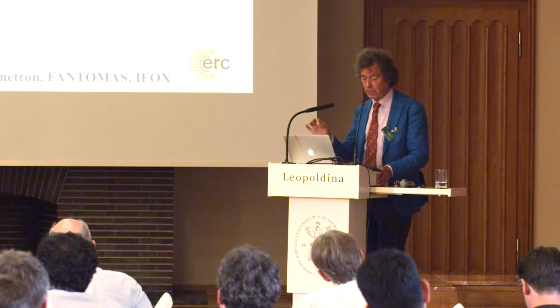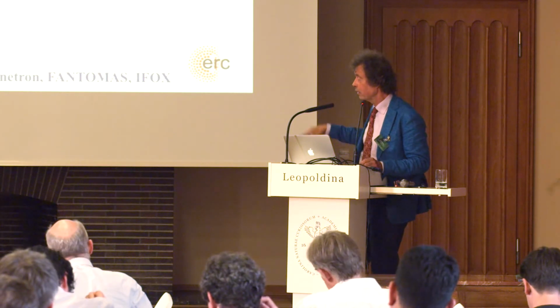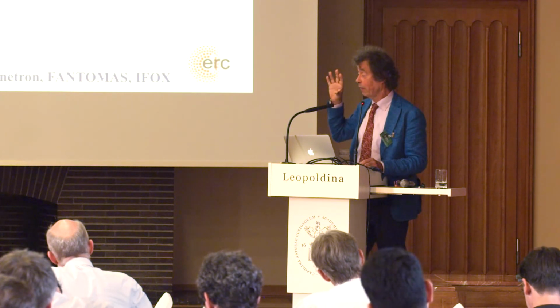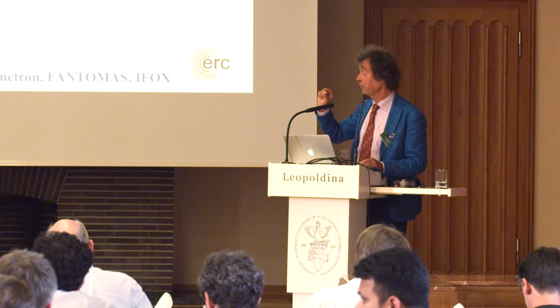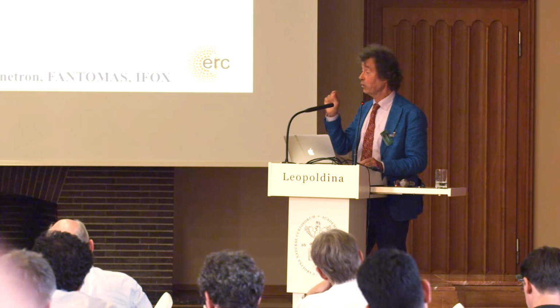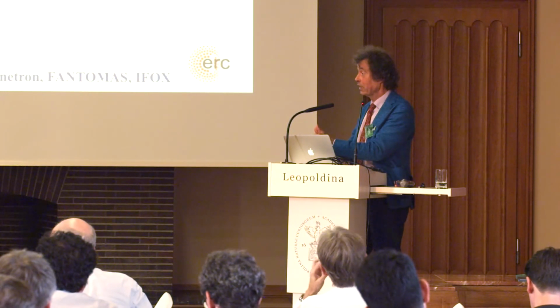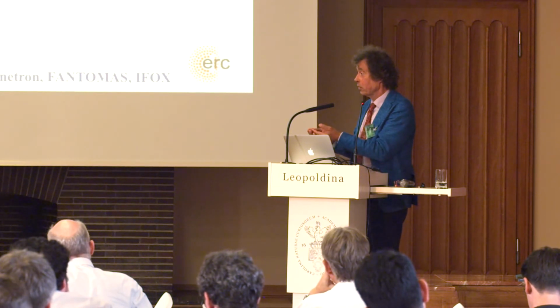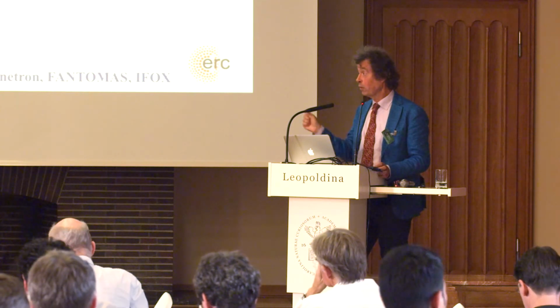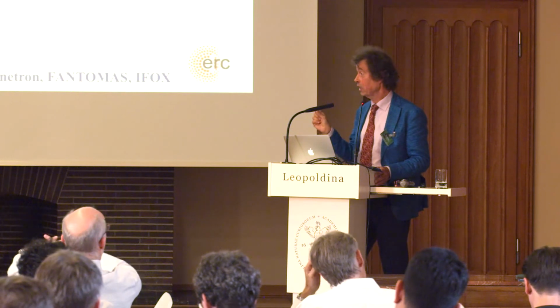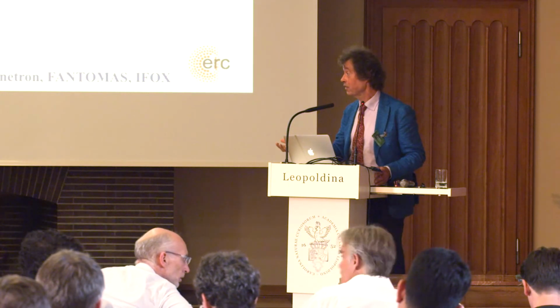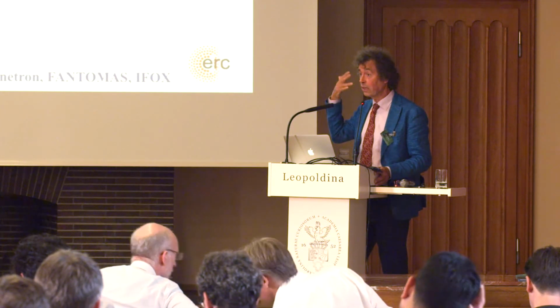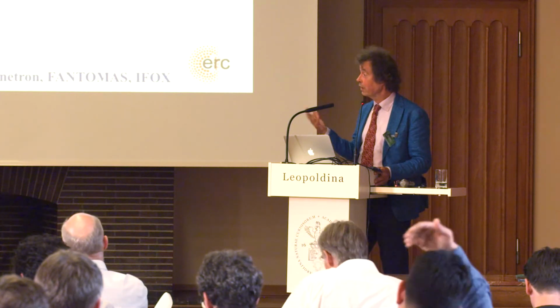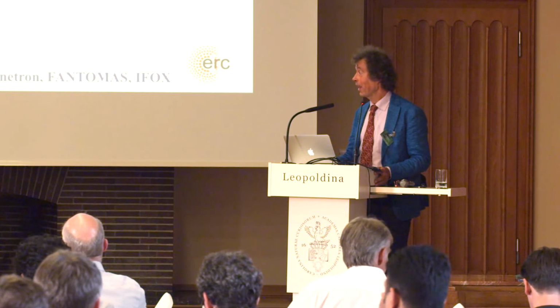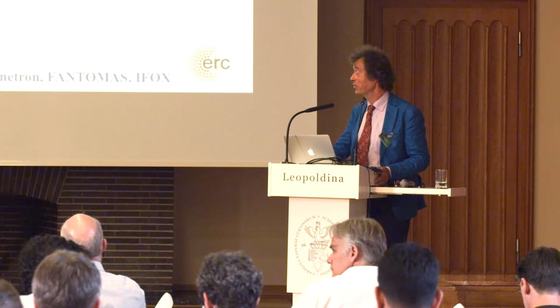Yeah, but what we do there, and this is why I'm still coming back to the way we are trying to approach it now, is that the way we have been able to switch the magnetic domains very efficiently with a femtosecond laser pulse is because we intrinsically use the exchange interaction between the spins. And we excite this with a femtosecond laser pulse. So we bring the system into a very strongly non-equilibrium state, but we do it on a very short time. So the actual energy cost is low, and it's the material itself that does the work, the exchange interaction, which is very strong. It's like 1,000 Tesla. And so this gives us the idea of using light to let the material do the work. There's still a long shot to real materials that can do it by themselves and learn. But I think there are very good reasons to do it in that way.